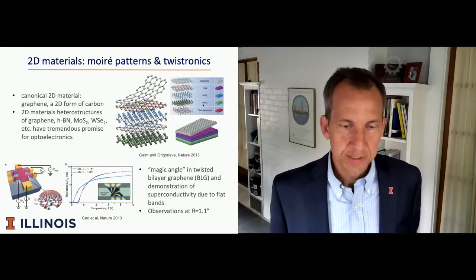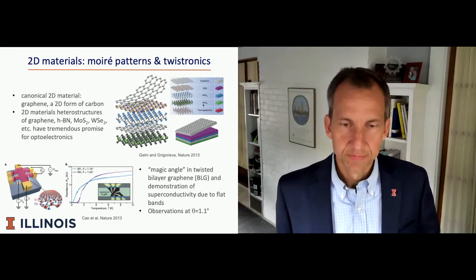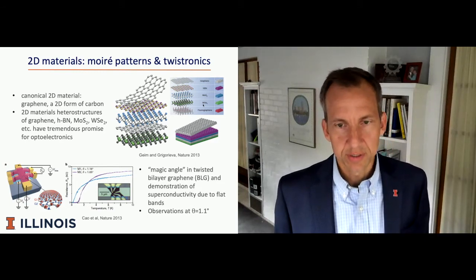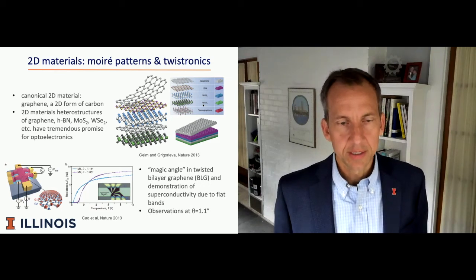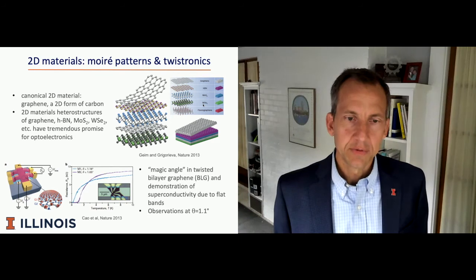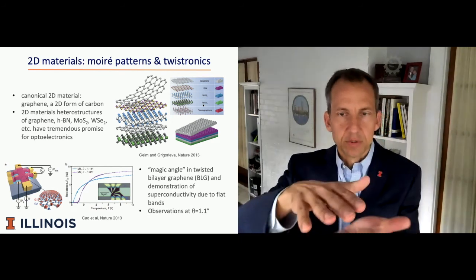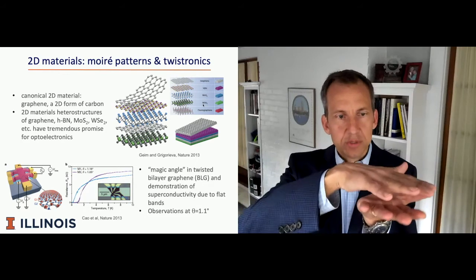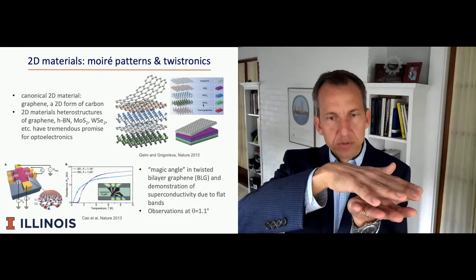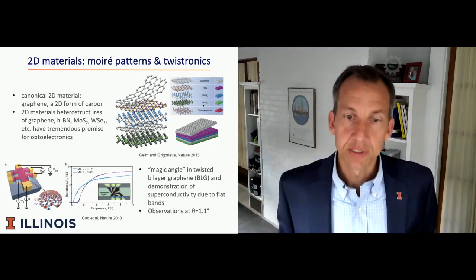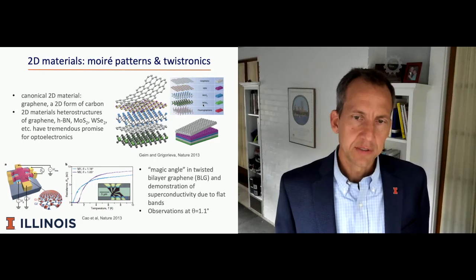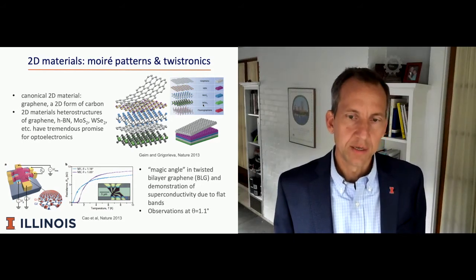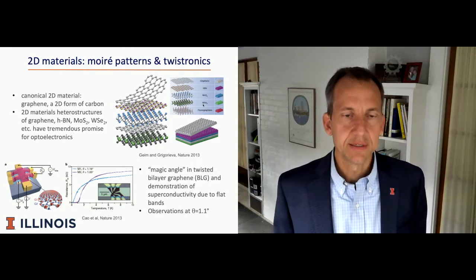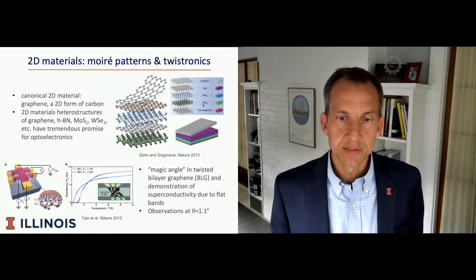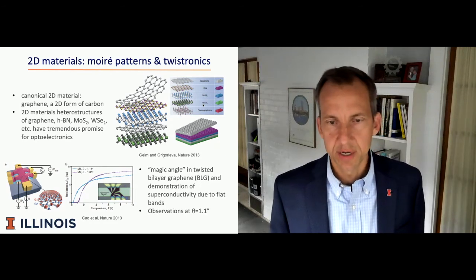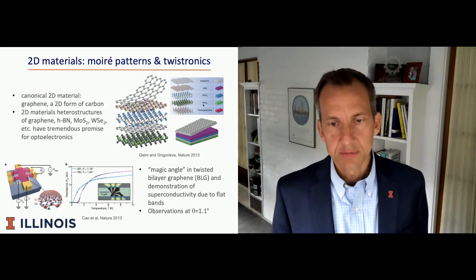Now, in terms of the emergent properties that one might hope to discover, probably the most well-known such property was observed a few years ago in bilayer graphene. And in this system, one looks at a stacked 2-layer graphene structure that has a small twist angle between the 2 layers. So we call this twisted bilayer graphene. And there's observation of special properties that occur when the twist angle is precisely, in this case, 1.05 degrees. So that's a very small rotation of the top layer relative to the bottom layer, at which one can observe